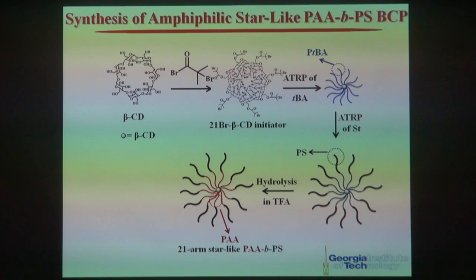in blue. So why is it 21 arms? Because we have 21 hydroxyl groups. All these can be converted into bromine functionality, allowing you to grow polymers with 21 arms. After that, we performed the second atom transfer radical polymerization of styrene, yielding this multi-arm star-like poly(tert-butyl acrylate) inside and polystyrene block outside. And finally, we did the hydrolysis in acid, this trifluoroacetic acid, yielding this 21-arm star-like polyacrylic acid-block-polystyrene. Now the inner block is hydrophilic and the outer block is hydrophobic. So it is amphiphilic in nature.